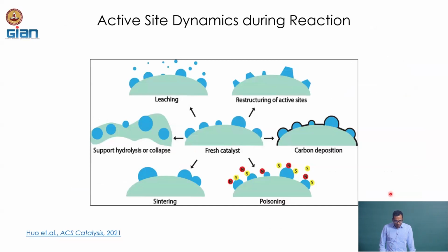But what we discussed previously is that for a long time it was believed that catalysts do not change during the reaction. But for modern-day catalysts, especially heterogeneous catalysts, there is a fair chance that dynamics will happen because of the reaction environment. What we see at room temperature, open to atmosphere, changes when we do the reaction where the temperature is different, the pressure is different, and the gas environment is different; the transformation will take place. So, here are some examples in cartoon form of how these transformations may happen, or the typical ways the catalyst active site dynamics happen.